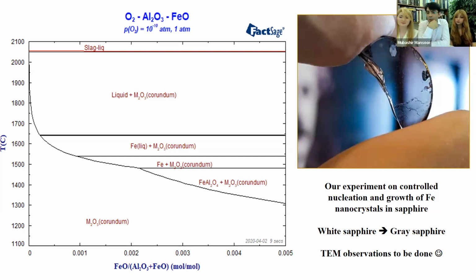The previous process requires very high temperatures to be done easily in a short time frame. So you would always have these stress halos and very similar phenomena that are observed in sapphires that have been treated at a high temperature. Stress halos are a very good indication, but also, due to the limited amount of oxygen present in the furnace, you should always have some concentration of oxygen vacancies. Our calculations show that oxygen vacancies are responsible for a chalky appearance under UV, I mean, under fluorescent lights. So if you shine a UV light and you see some chalky appearance, and you also have these stress halos and indications of high temperature heating, then it is extremely probable that the material has gone through this sort of heat treatment.